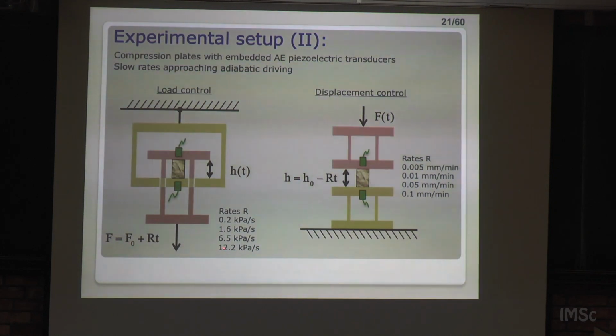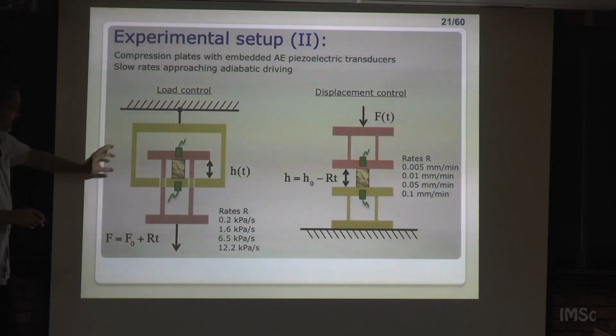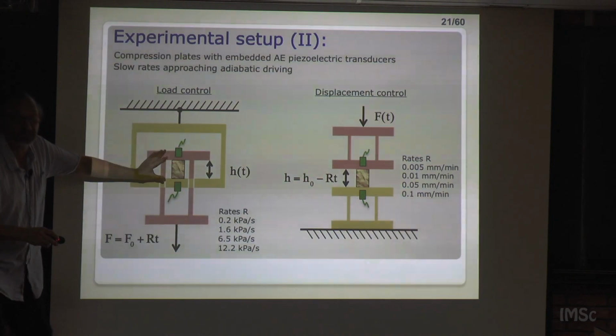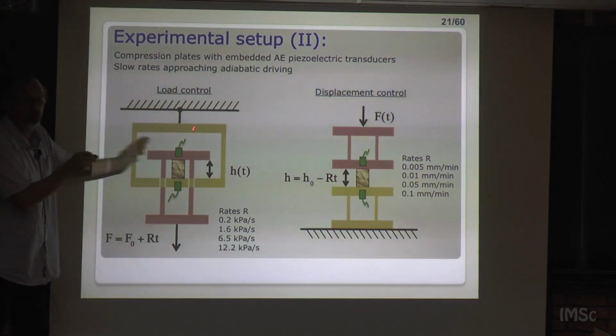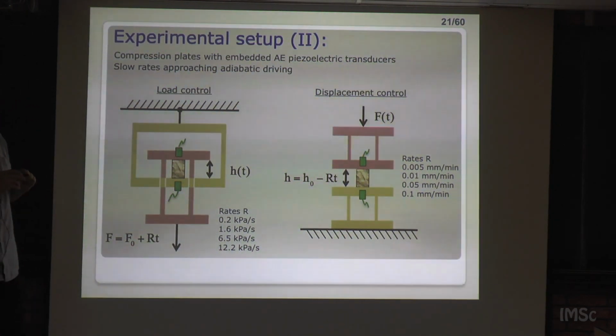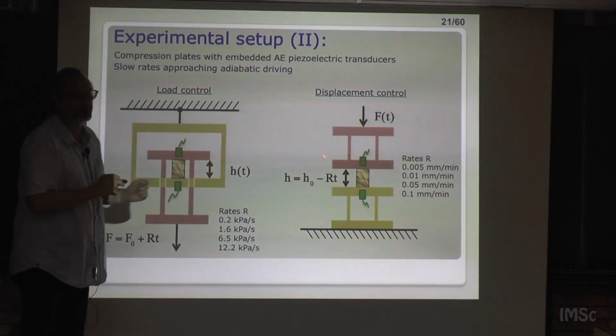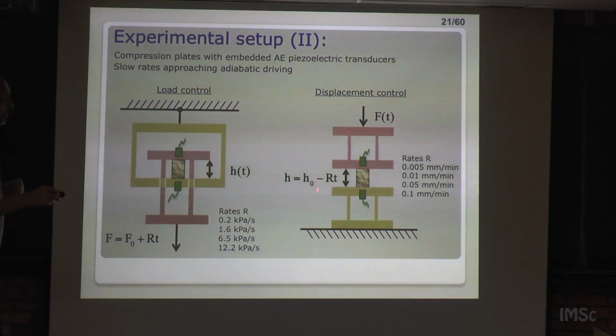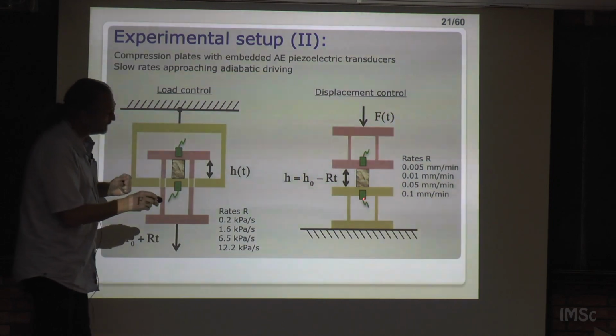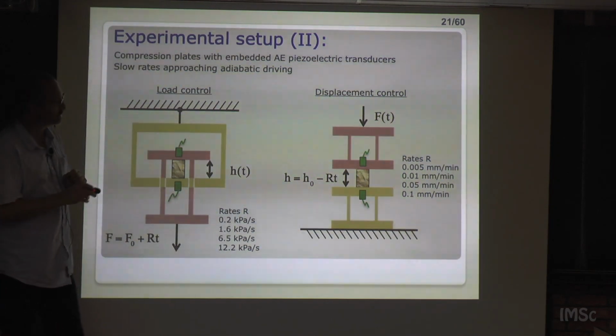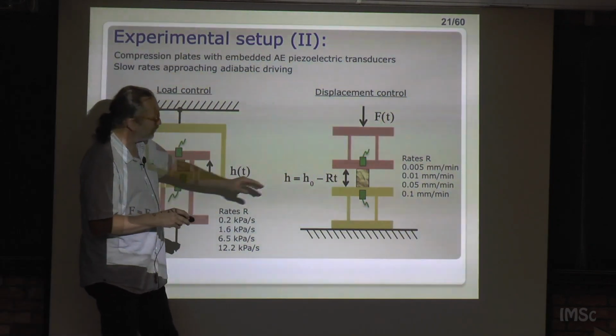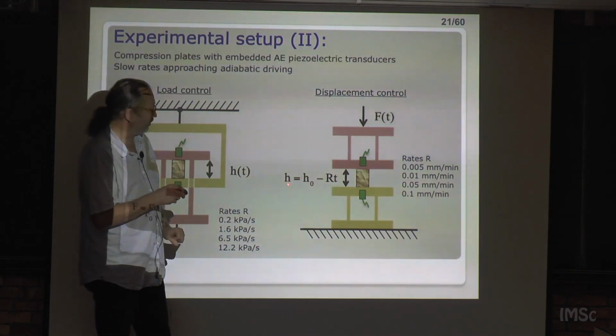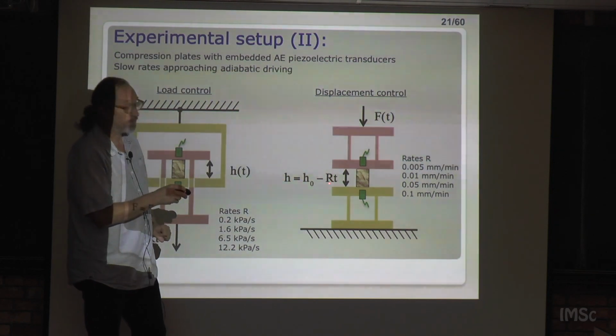And what we measure with a laser extensometer is the height of the sample that decreases, together with the acoustic emission that I will tell after. In the other experiment, this is called displacement control. The sample is here. We also have the embedded acoustic emission sensors. But what we do is to keep the machine compressing at a constant rate. So the height of the sample is proportional to time.